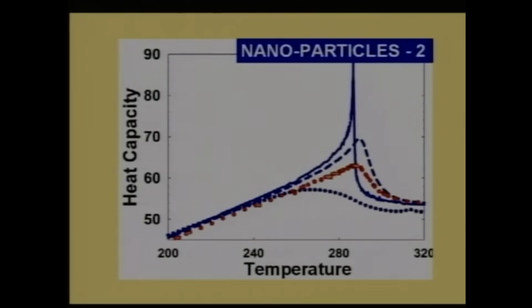These new results were completely unexpected because they run counter to prevailing views on what happens at the small scale. It is the broad features in the first nanoparticles that are consistent with other measurements and predictions. Since the two sets of nanoparticles are essentially the same size, the difference cannot be a particle size effect. What are they due to?